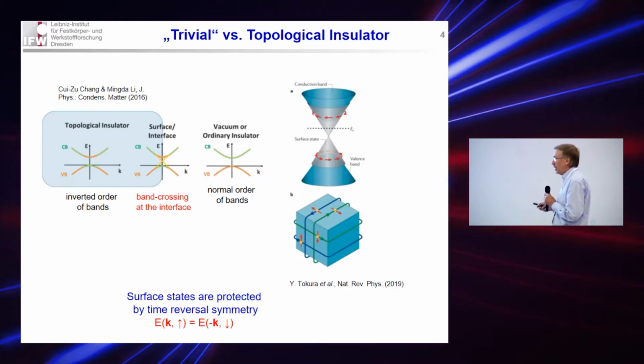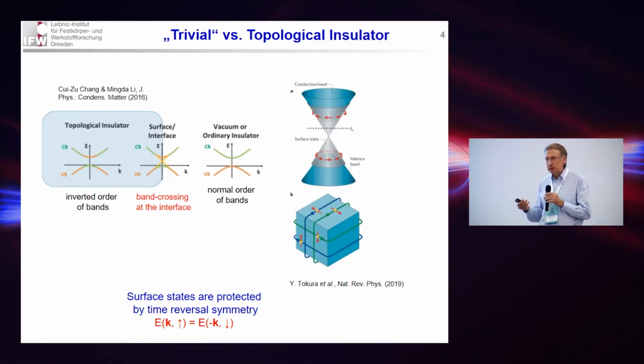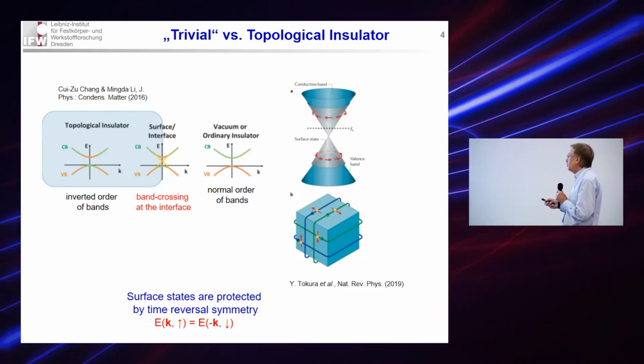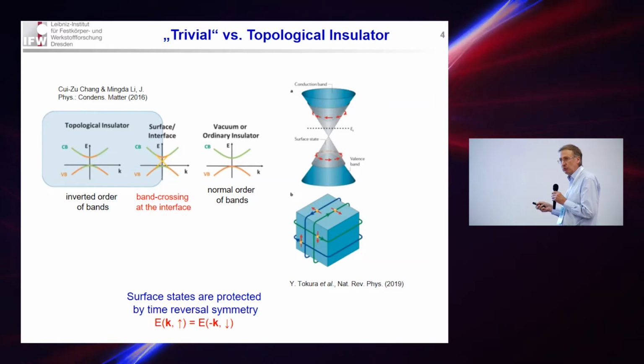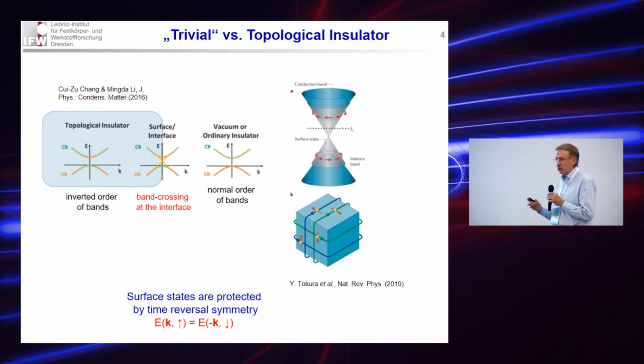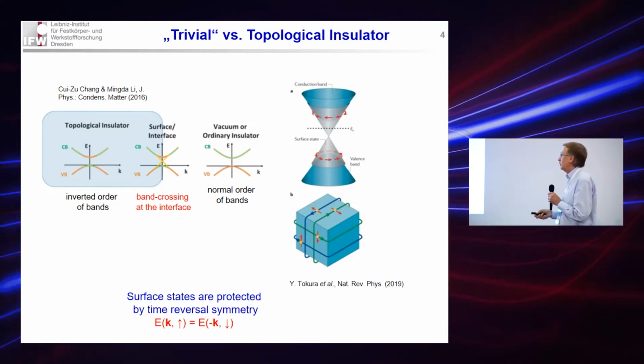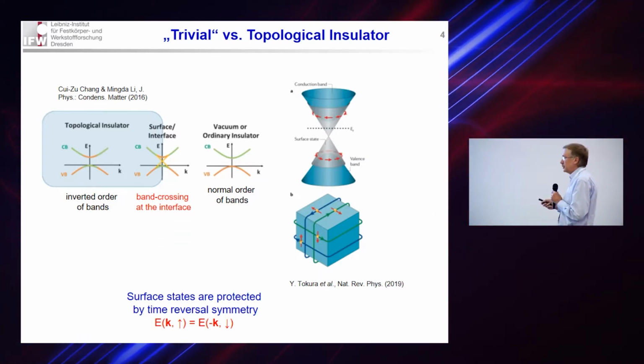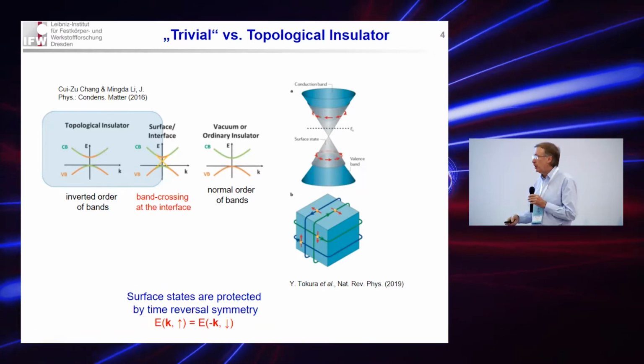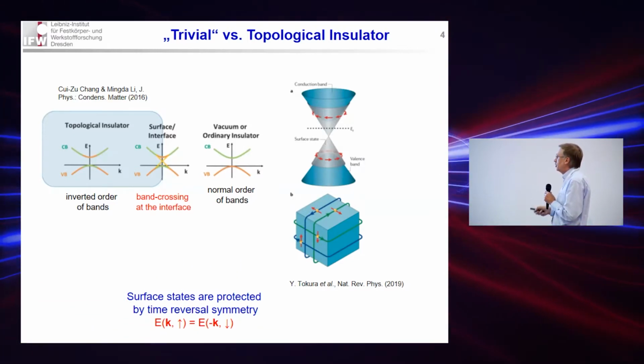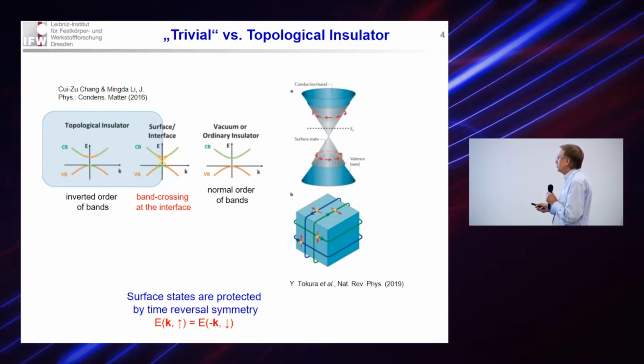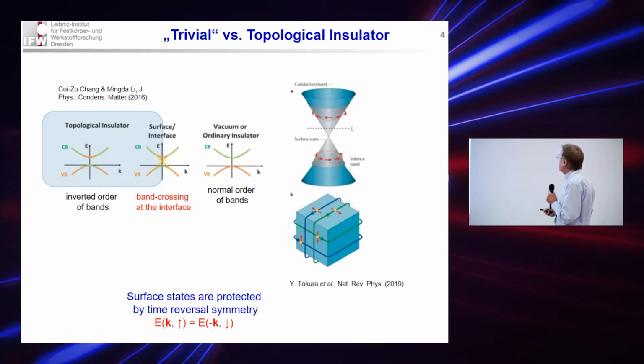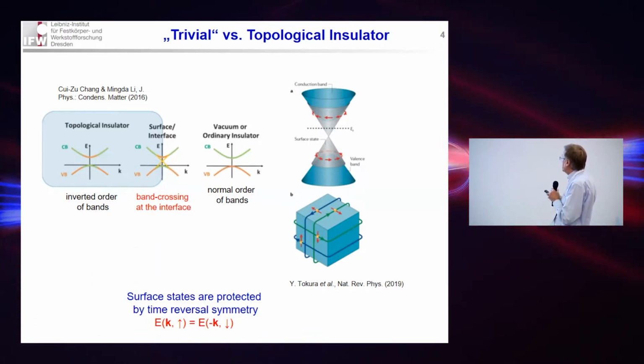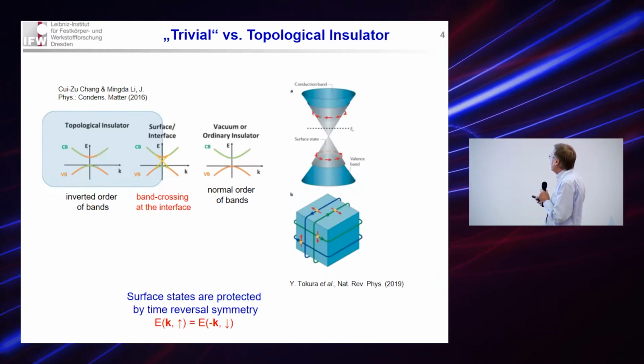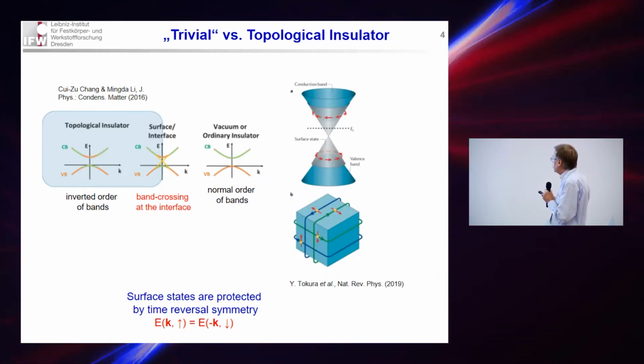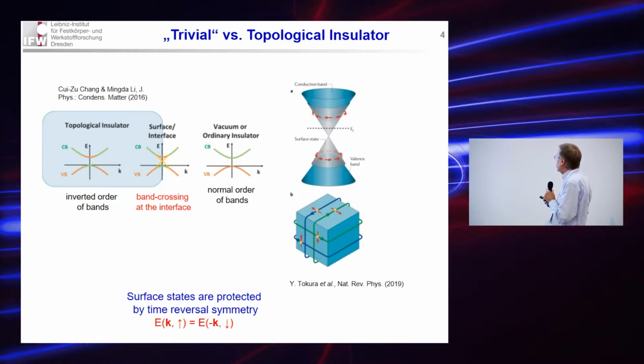This inversion of the bands can take place only in this material. That means that at the interface either with vacuum or with a conventional insulator, where the spin-orbit coupling is absent or very weak, this original order of the bands should be restored, and inevitably this inverted band should cross on the surface. So in the bulk it is an insulator, but at the surface there should be conducting states. This is visualized in this graph from the paper of Hasan et al., where these surface states form Dirac cones with linear dispersion.